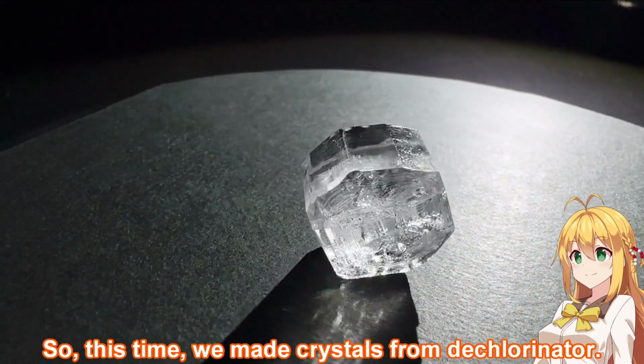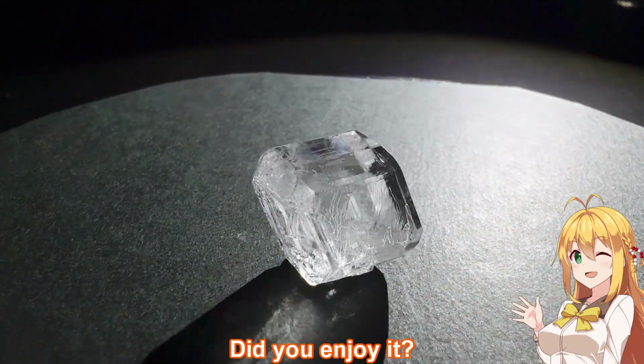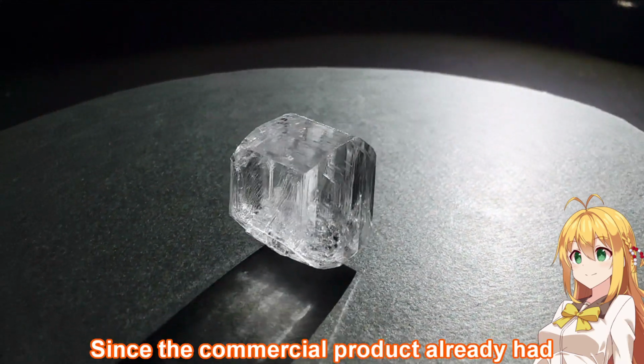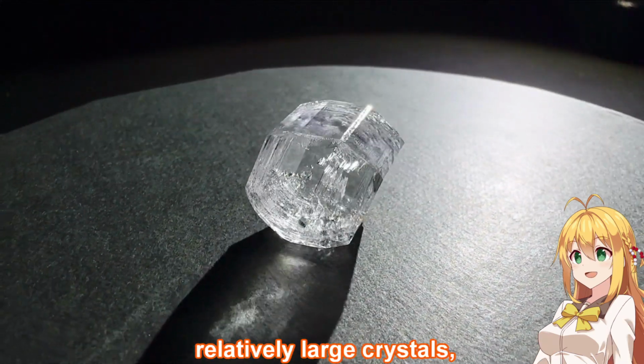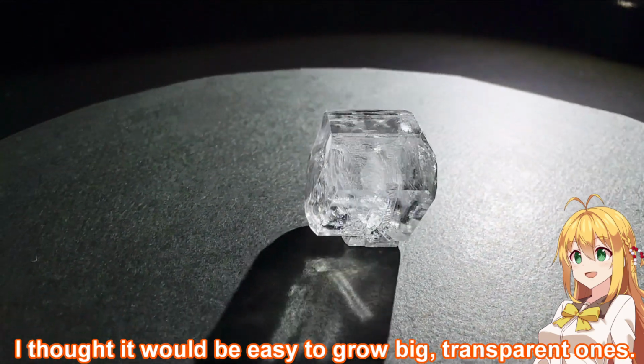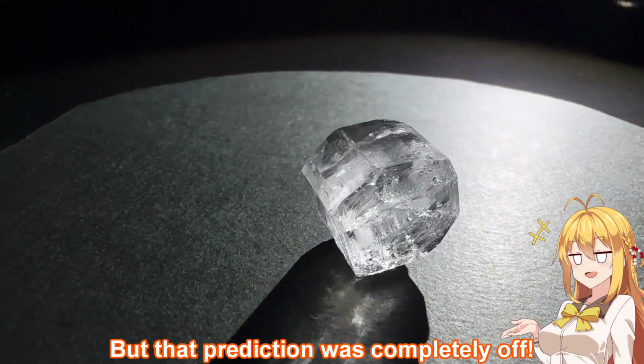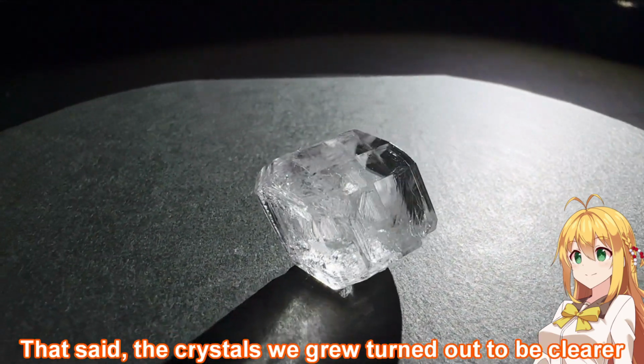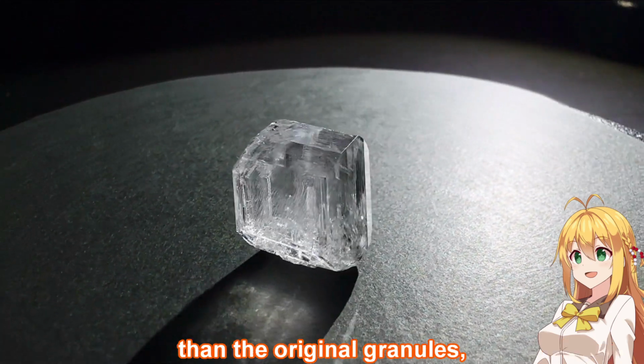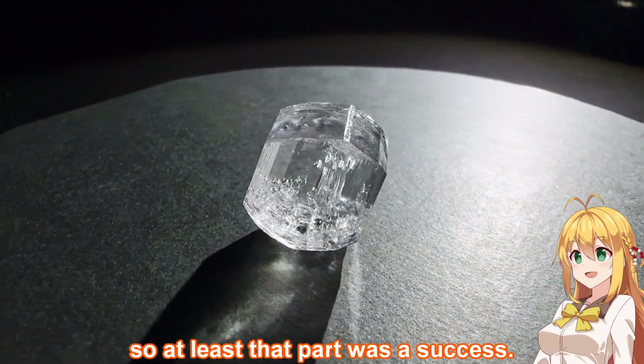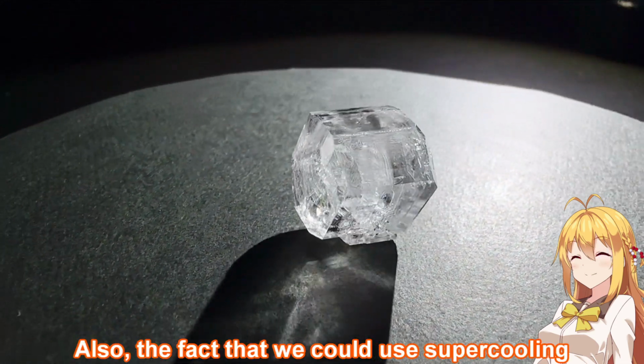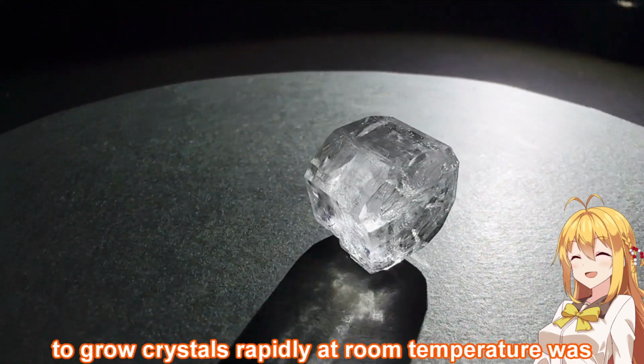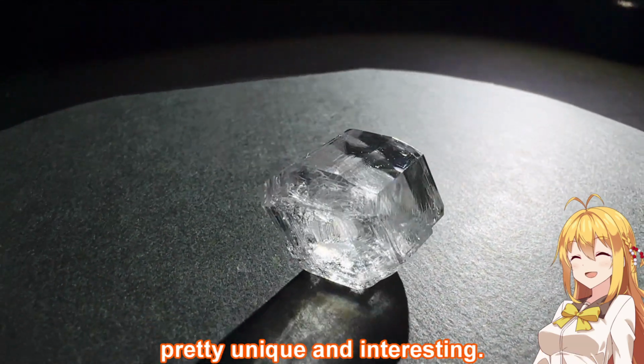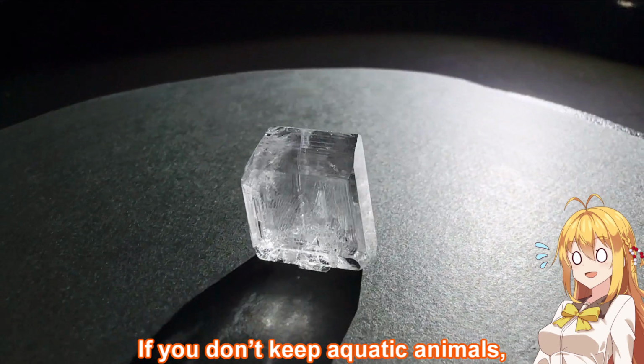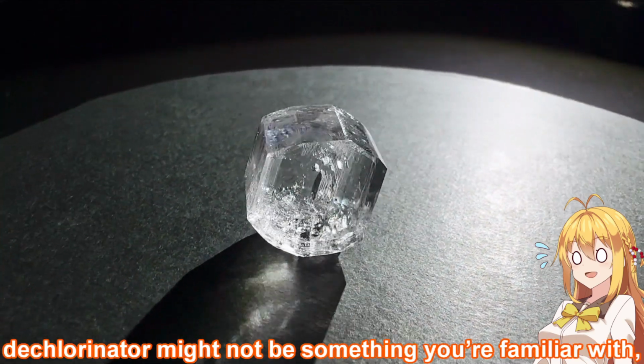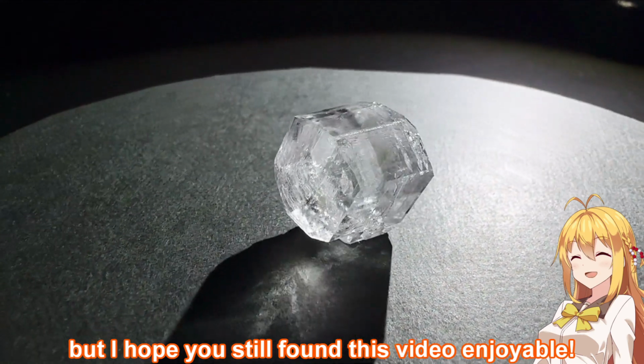So this time, we made crystals from Dechlorinator. Did you enjoy it? Since the commercial product already had relatively large crystals, I thought it would be easy to grow big transparent ones. But that prediction was completely off. That said, the crystals we grew turned out to be clearer than the original granules, so at least that part was a success. Also, the fact that we could use supercooling to grow crystals rapidly at room temperature was pretty unique and interesting. If you don't keep aquatic animals, Dechlorinator might not be something you're familiar with, but I hope you still found this video enjoyable.